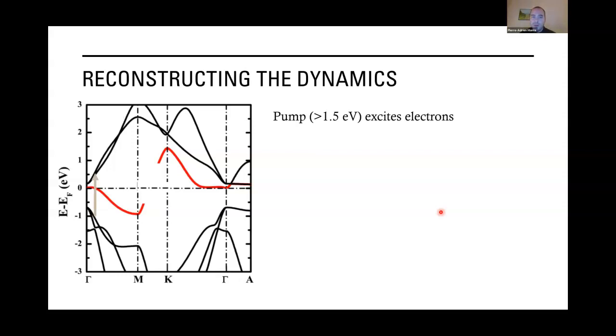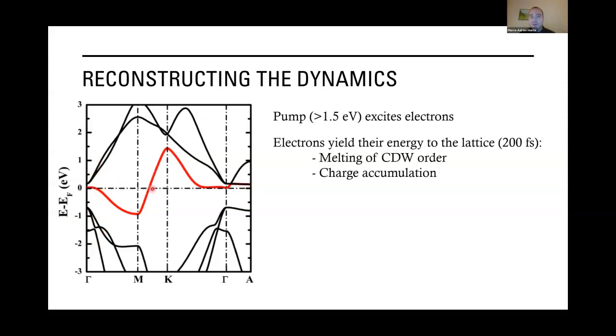So first, our pump is going to excite electrons from this sulfur band to the tantalum band. Then through electron-phonon coupling, we are going to have a melting of the charge density wave order. And at the same time, electrons are going to accumulate at the M point and holes at the gamma point. They are going to recombine through electron-hole recombination. And this is really one of the first times that this mechanism is observed in this tantalum disulfide, but it could also be applied to tantalum diselenide that also has a similar type of band that is not crossing with other valence bands.